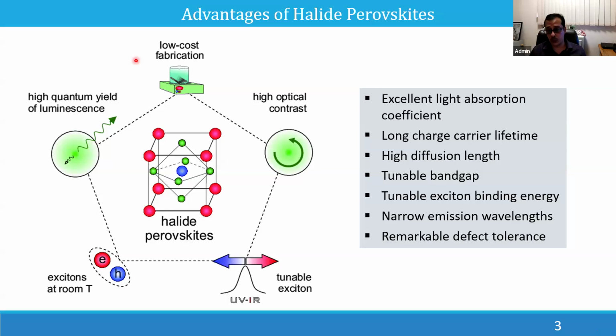Similarly, the band gap can be tuned. For example, for solar cell applications, you may need a band gap of 1.5 electron volt, and you can easily tune that by incorporating tin or lead, or by changing the organic component of the material. I will discuss the structure in the coming slides. And you can also tune the exciton binding energy by changing the quantum confinement properties. You can easily tune the binding energy, and you can narrow the emission wavelengths if you require a narrow band gap, or if you require a broad band gap.